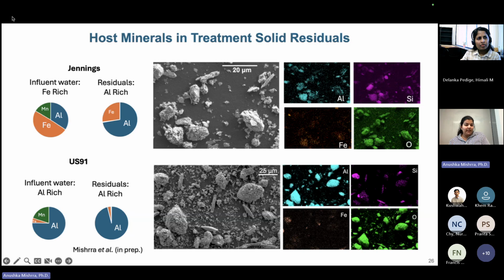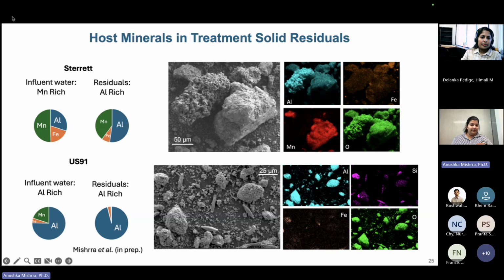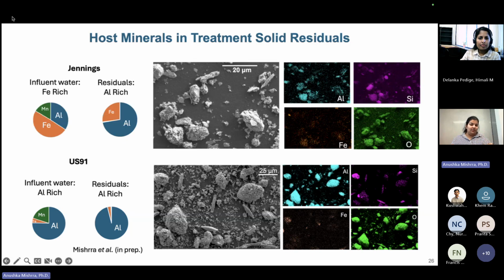We see very little iron around these particles. And the fact that there's a lot of aluminum present with silicates makes me think that when you have these residuals showing dominance in aluminum, you're definitely going to see a lot of aluminum. But the secondary element that is dominant may or may not show up in the maps. For example, just going back real quick, for Sterret manganese we were able to see, but here iron we're just barely able to see across these scans that we're doing.